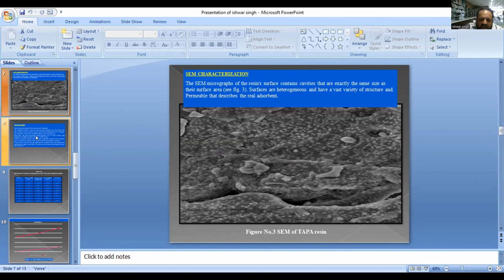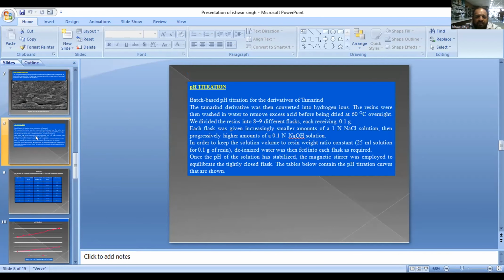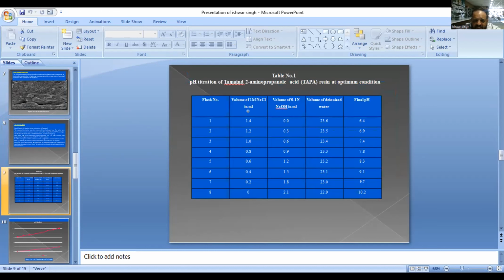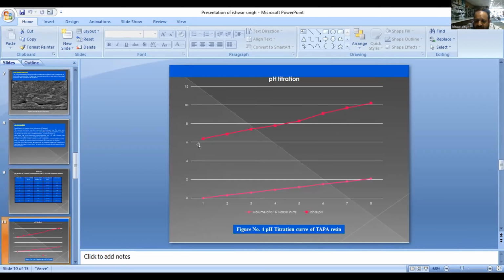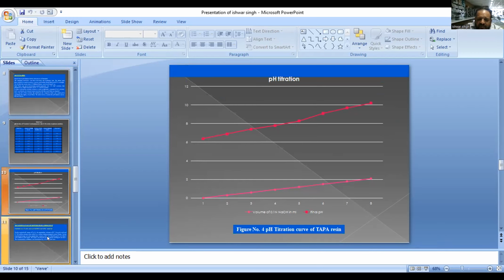That I have synthesized in the laboratory, and I did the pH titration. Based on the pH titration of the tamarind derivatives, the pH graph shows that it comes toward the basic side. As we increase the volume of NaOH with NaCl, the final pH is increasing. That shows the straight line curve, and this is the final pH. It is almost a straight line curve as we increase the volume of 0.1 N NaOH in every ml, and this shows that pH is increased in increasing order. So this shows that the resin is basic in nature.